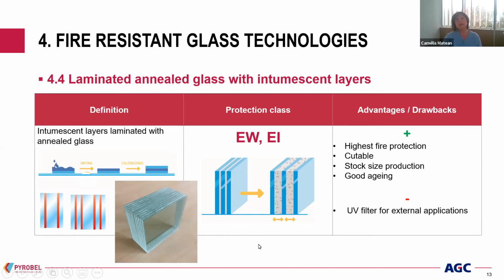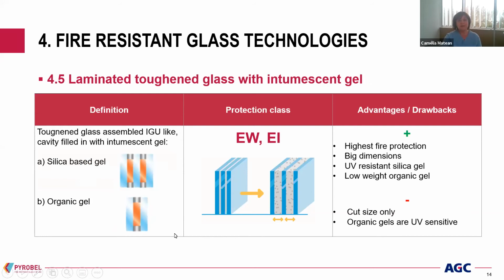The advantage of this kind of glass is the highest fire protection. It's a cuttable glass. It can be produced in stock size, so a good service. There is no problem of aging, it is good. The main drawback is that the intumescent interlayer is sensitive to UV, and for external application, a UV filter is needed. And the last but not least category is laminated toughened glass with intumescent gels, also in the EI category.